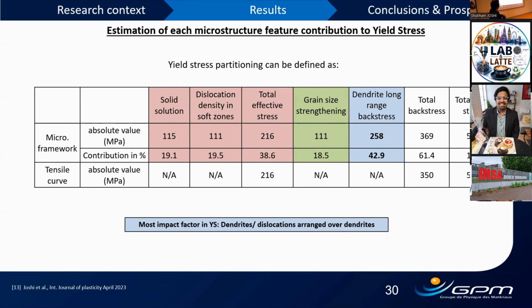If we look at grain size strengthening, it is 111, and the dendrite long-range back stress is 258. So the sum is 369, which is quite similar to the experimental value. So we do not have a lot of error. And the total yield stress that we could predict from this model again quite matches the experimental value. And so this shows that the model makes sense.